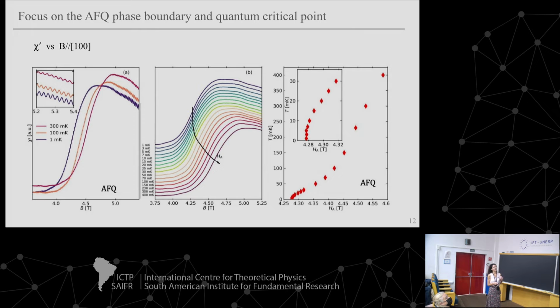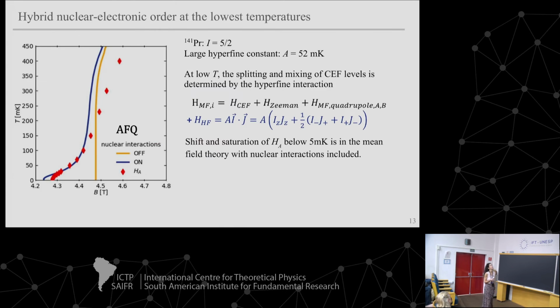Okay, so how does this compare to our predictions, and how can we understand what's going on there? To remind you what we were doing with our calculations, we have the mean field Hamiltonian with the crystal field term, the Zeeman term, and the quadrupole term, and that's the yellow line in this plot. So it just should saturate at low temperature. When you add the hyperfine term, you get the blue line, and that gave us this shift of the phase boundary and a saturation also at low temperature and at lower magnetic field.